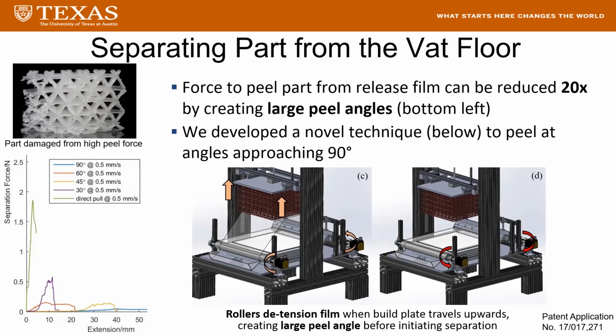And by peeling off the release film from our cured structure at these high peel angles, we're able to decrease the separation force by over a magnitude compared to if we just tried to lift the part straight off of tension Teflon.